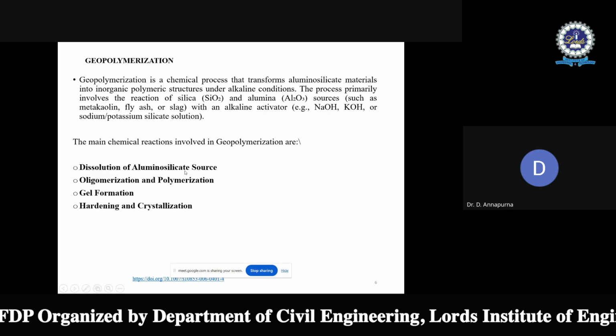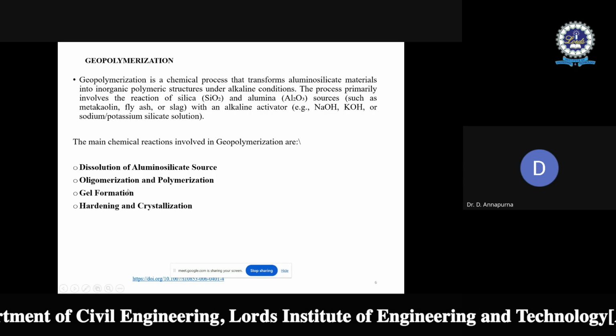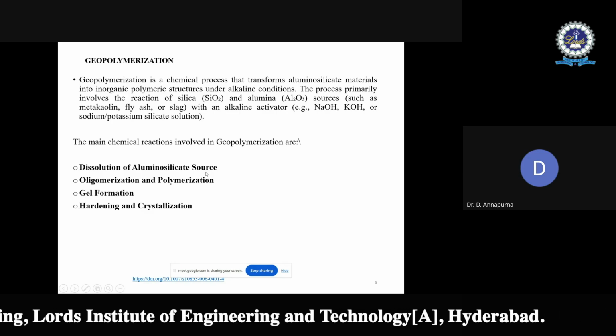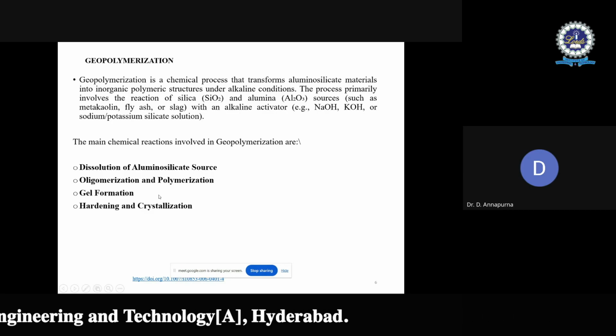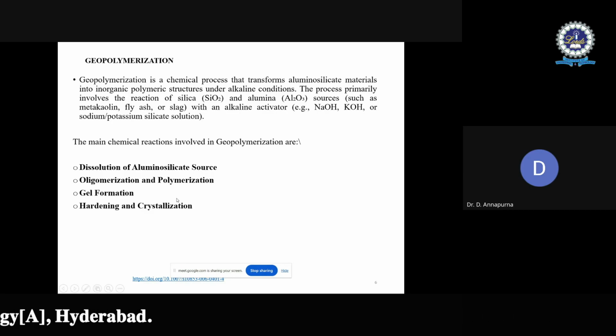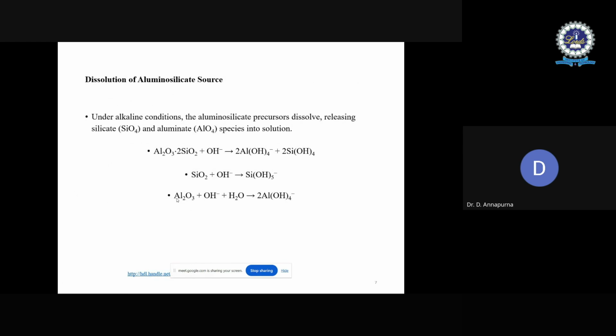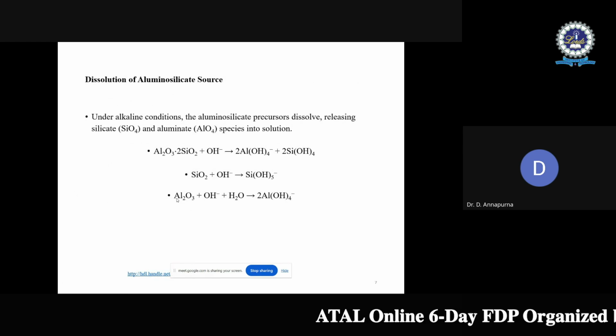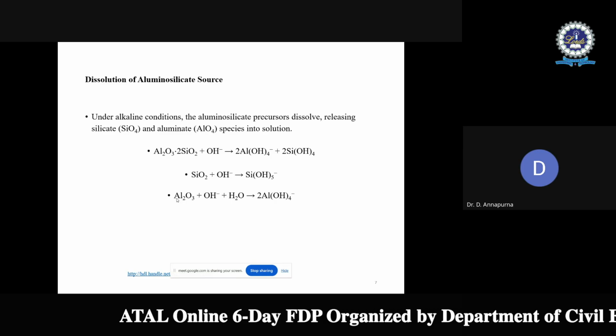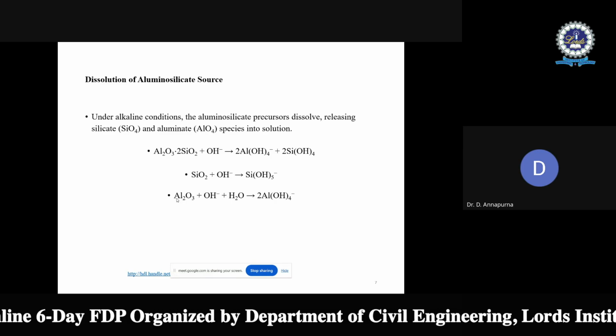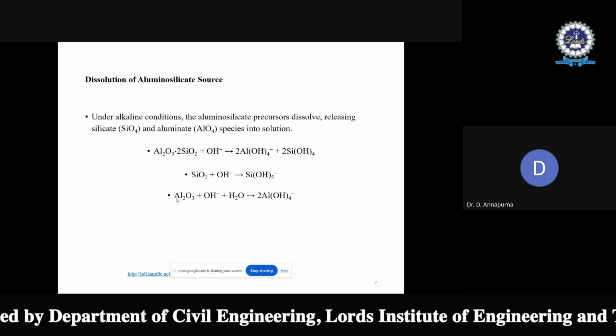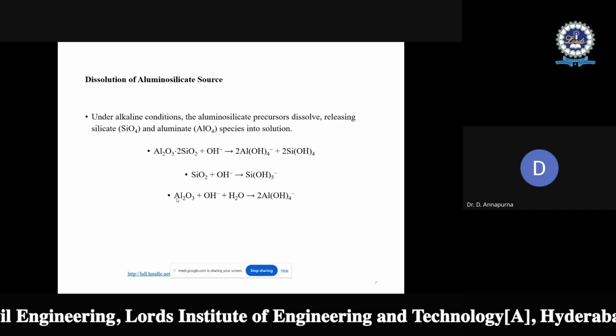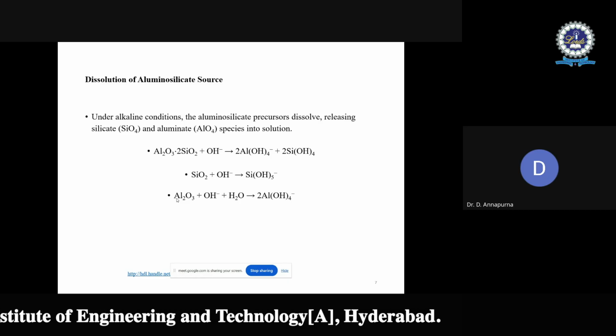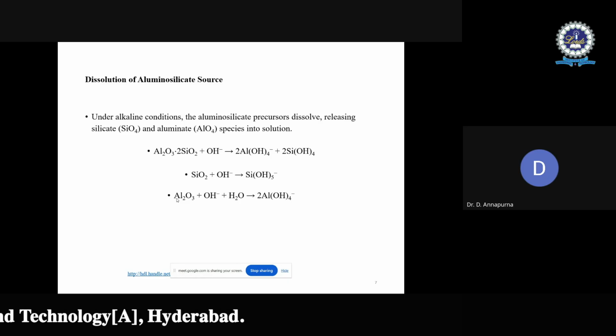First stage will be the dissolution of aluminosilicate source. Second will be oligomerization and polymerization. Third will be gel formation. Fourth one will be the hardening and crystallization. First, dissolution of aluminosilicate source. Under these alkaline conditions, the aluminosilicate precursors, I said fly ash, GGBS, which are rich in alumina silicate, will be dissolving under the alkaline solution and releasing silicate and aluminate phases.